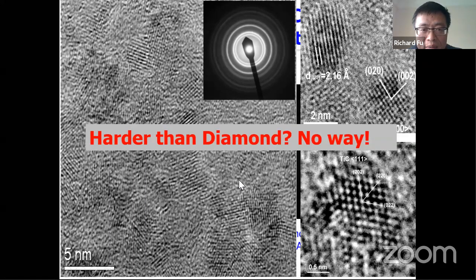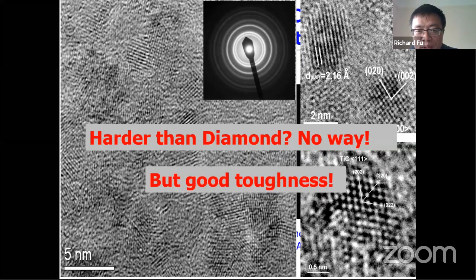The aim at the beginning was to get a coating as hard as, or even harder than, diamond, because in principle, through theoretical analysis, you can achieve a coating much harder than diamond. But we have done so much work and have never reached near the diamond level yet. Even though we cannot increase the hardness or strength significantly, we actually achieve very good coating toughness. That means the coating can prevent cracking and peeling off quite significantly. For engineering applications like cutting tools, we require not only hardness but also toughness as a very important parameter.